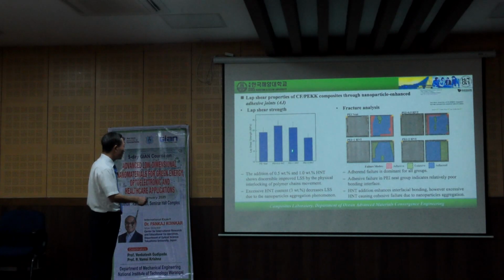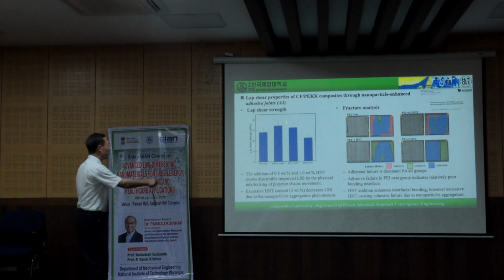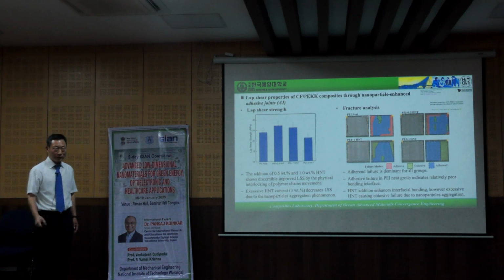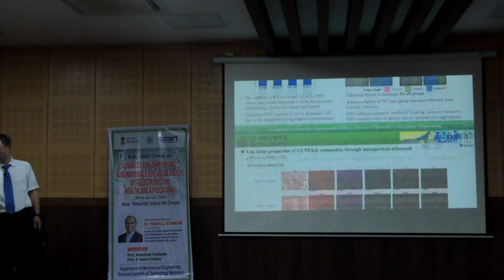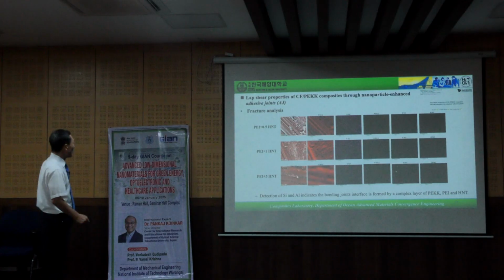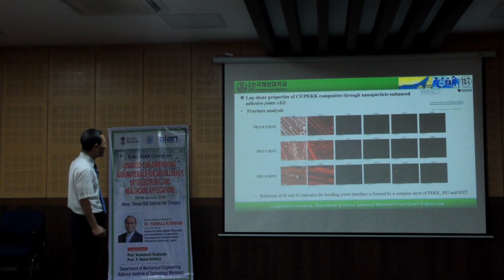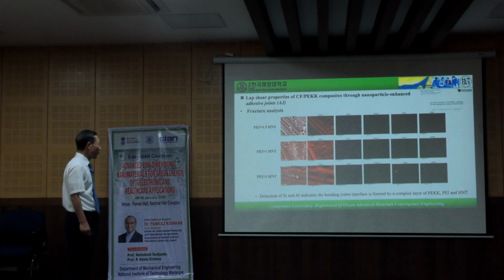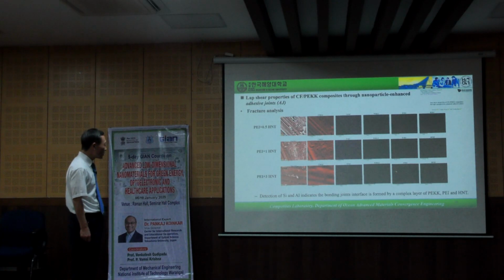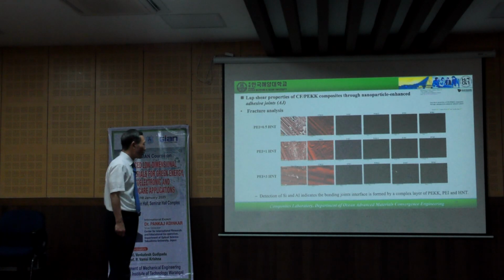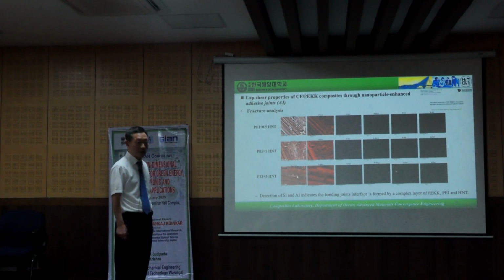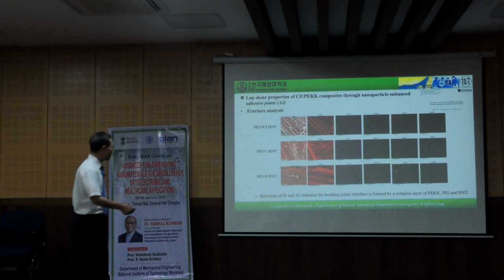Over 0.5, it decreases. So we finally used this 0.5 result. Also, we observed the fracture pattern, 0.5, 1, 3. Detection of Si and Al indicates the bonding joint interface is formed by the complex layer of PEI and HNT. Situation is like this.